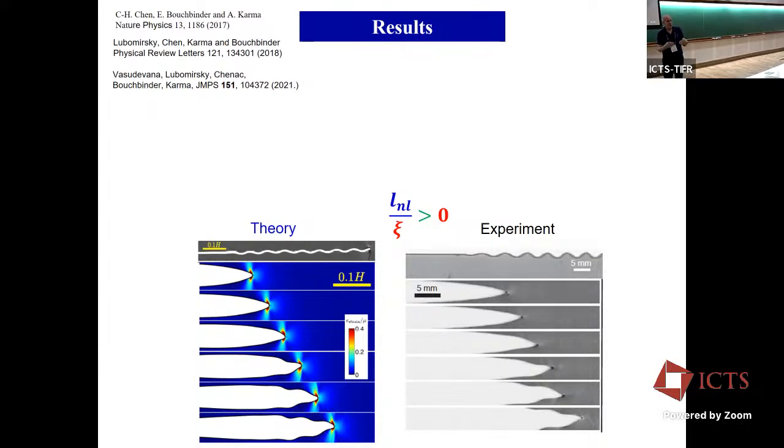So the higher the energy flux, the smaller the curvature of the crack tip. And so what you're seeing is that the crack, well, you don't see it very well here, starts more sharp and then gets more blunt as it's accelerating. So that's just linear elasticity.